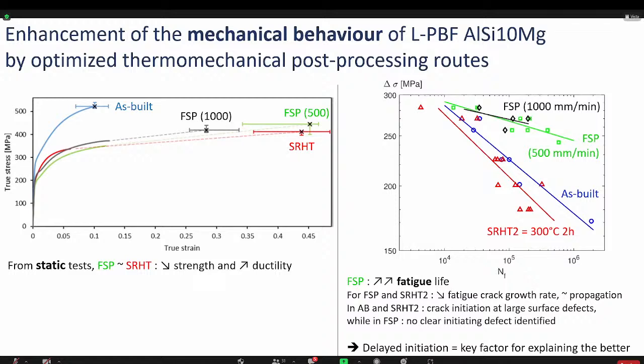While if you look at the initiating defect, in the as-built and the stress relief material, we can quite commonly see a very large defect close to the surface identified as the initiating defect. While in the FSP material, we cannot clearly identify any initiating defect. So the delayed initiation is really the key explanation to justify this improvement of the fatigue life after FSP.